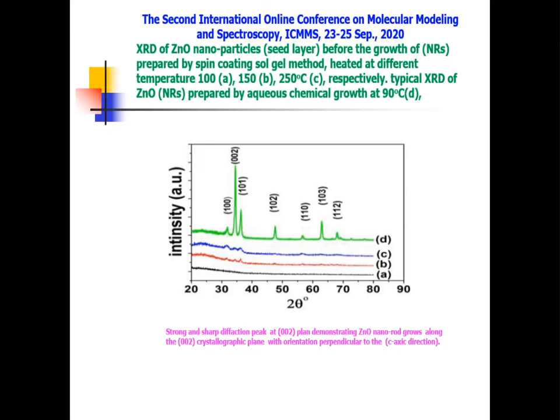Here we have an X-ray of the zinc oxide nanoparticle seed layer heated at 100, 150, and 250 degrees centigrade, and then at the end those are three seed layers steps, and D was for the preparation and deposition of zinc oxide nanorod by aqueous chemical growth at 90 degrees centigrade. We can see a strong and sharp diffraction peak at the 002 plane, demonstrating the zinc oxide nanorod grows along the 002 plane with orientation perpendicular to the c-axis direction.